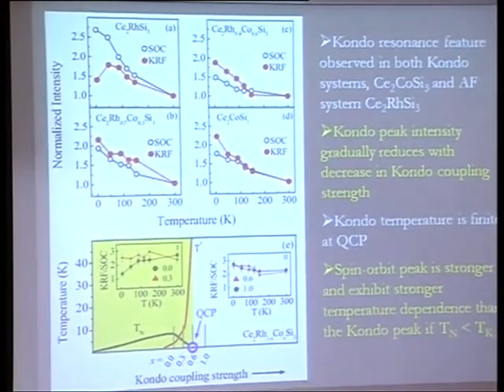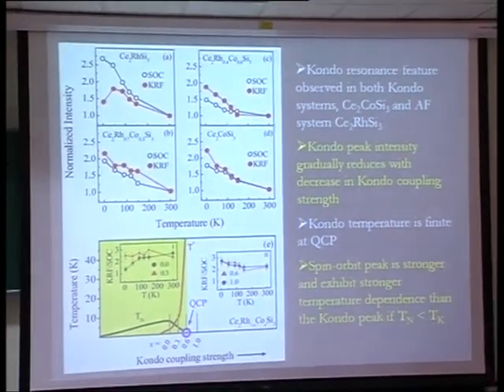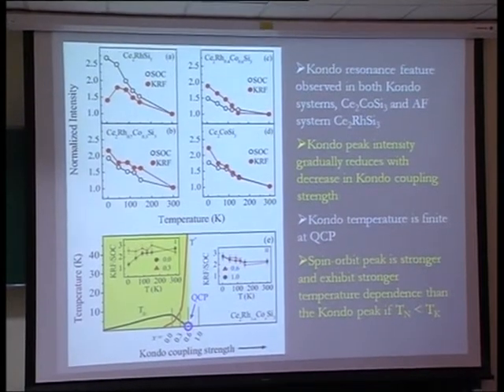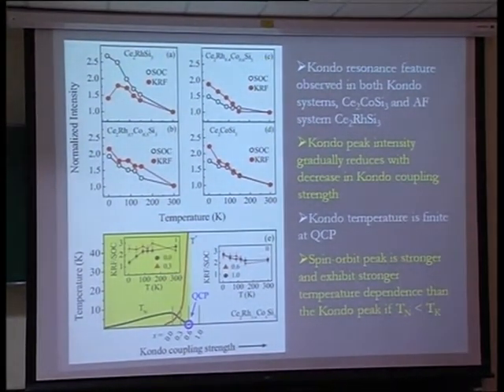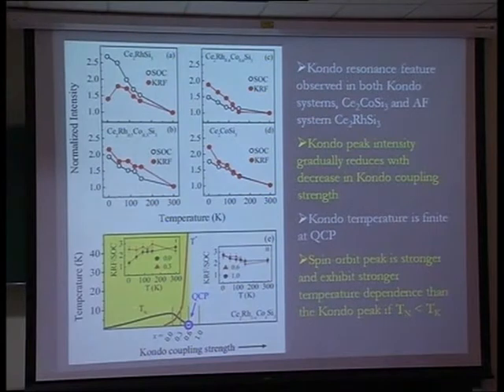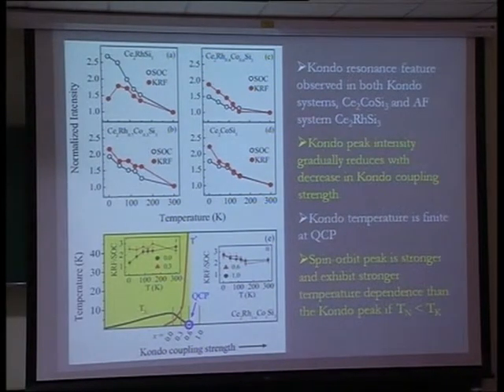Okay, so this is the strong coupling regime, where you can see that this intensity ratio goes up if you reduce temperature, and in this region where you have long range order, this intensity goes down. So what we find is that the Kondo coupling is actually finite within this long range order phase, but the spin-orbit coupling seems to be stronger compared to the Kondo coupling strength when you have this spin density wave quantum criticality. So that's the point which I wanted to make.